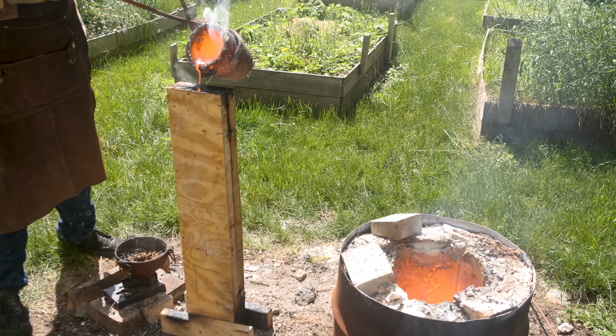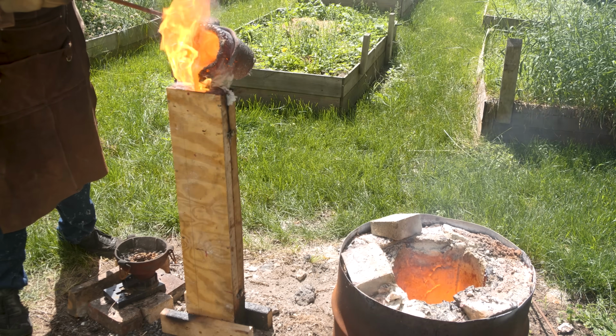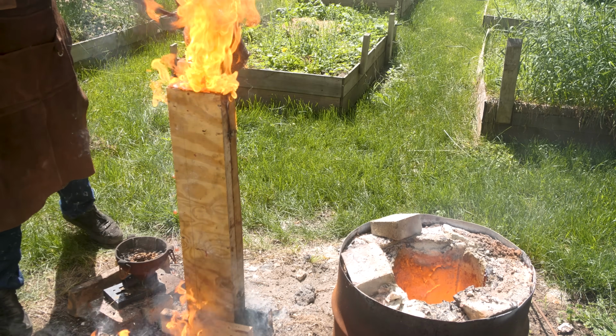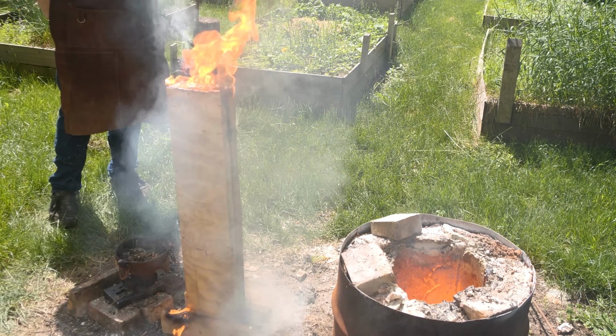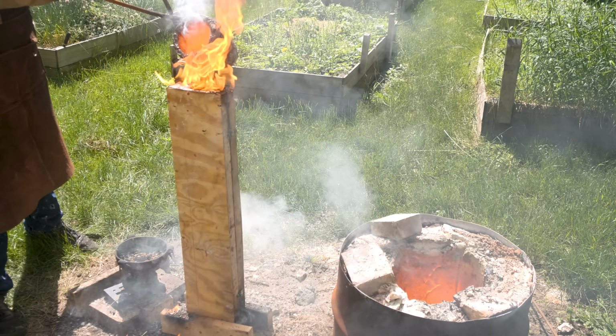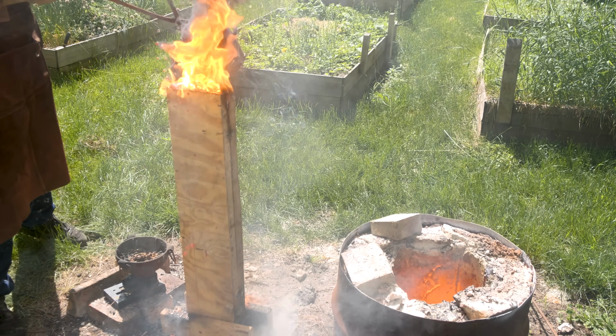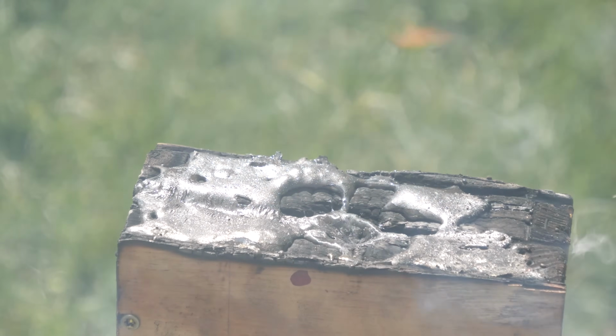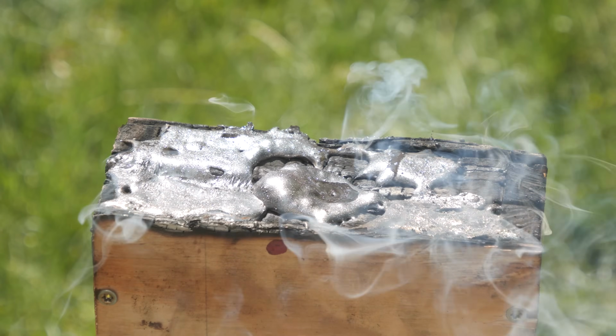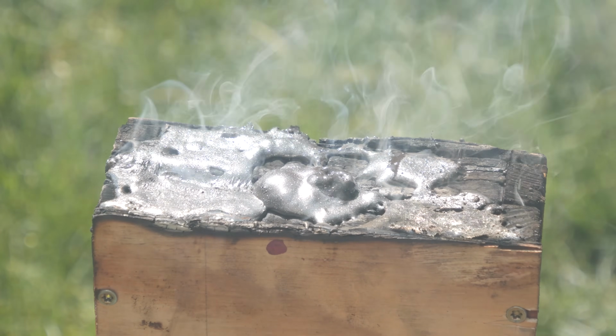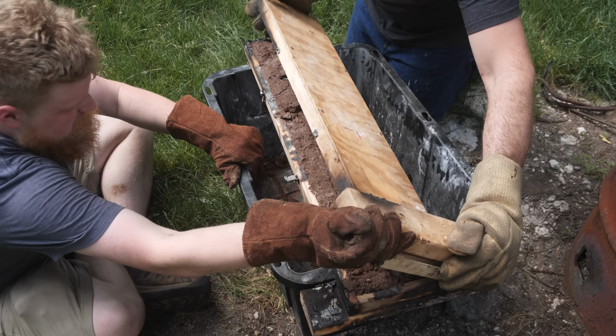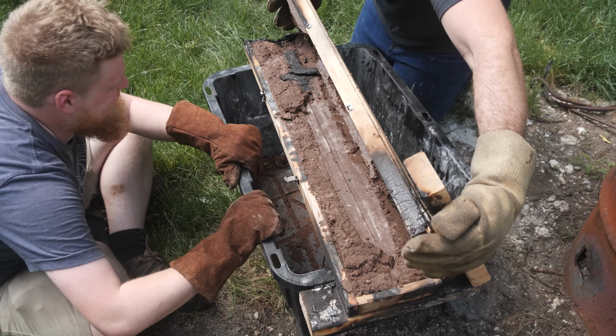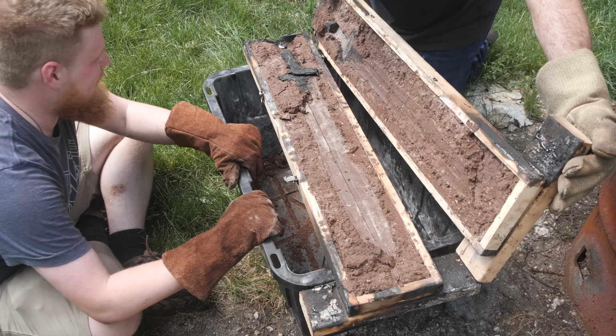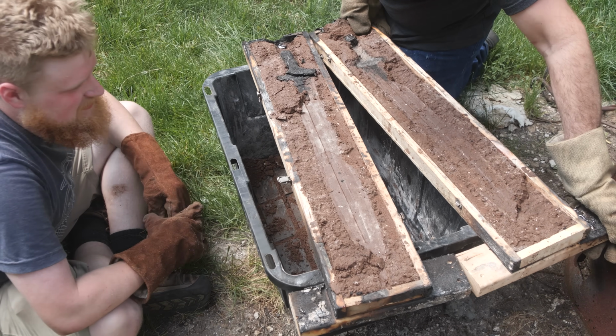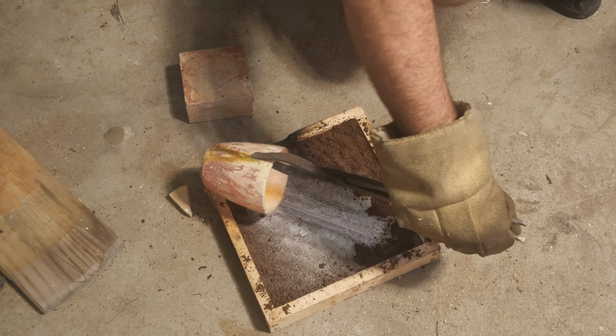In contrast to the table salt, borax was surprisingly viscous, coming out a little bit closer to metal, and it ended up being so viscous it actually solidified before filling up much of the mold. What I wasn't expecting was for it to turn black, looking almost like asphalt or tar. I can only assume this is from the graphite crucible. I've run into this a lot with glass making, that once it's molten, it just really wants to absorb anything that it touches. So you generally need to use a non-reactive crucible like alumina or porcelain.